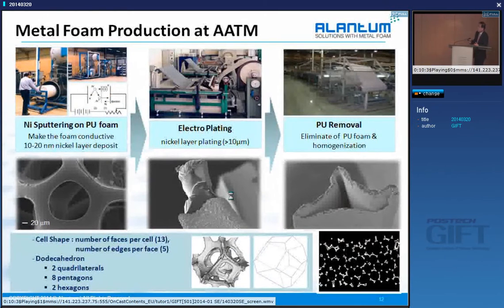Again, I told you that the polyurethane is non-conductive material. So with about 10 to 20 nanometer thickness sputtering or vapor deposition, we can make this polyurethane form conductive. Then we can move into the electric plating bath. So we can just dip into the electric bath, then we can coat maybe about 10 microns or 20 microns of nickel. Then still polyurethane is inside.